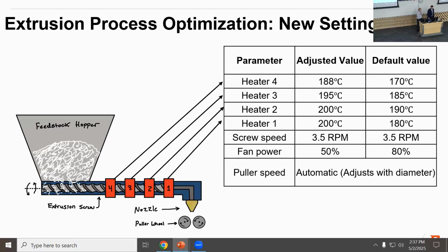As for the parameters I was talking about, I want to go over how the machine works a little bit more. As seen on the diagram, there are 4 heaters in red that each have their own temperatures, so we have those in the table. There's also an extrusion screw that has a set RPM that we can determine. And then the puller wheels at the end can be set as well. The main thing that we changed, though, was the temperatures, as we found that the material was just not melting very well. So we decided to go up to about 200 degrees, closer to the actual nozzle.